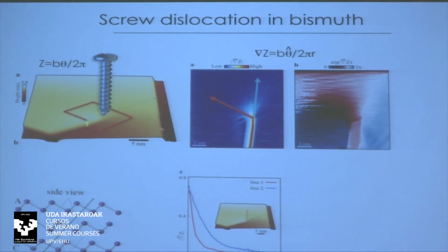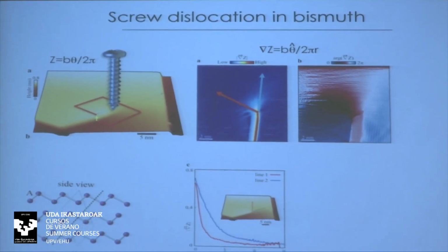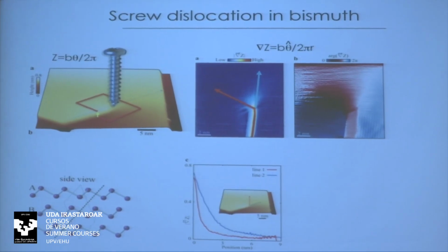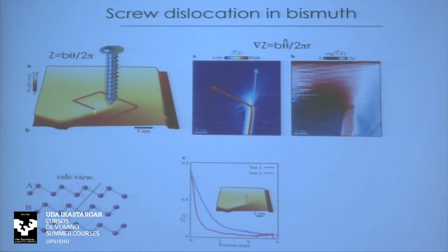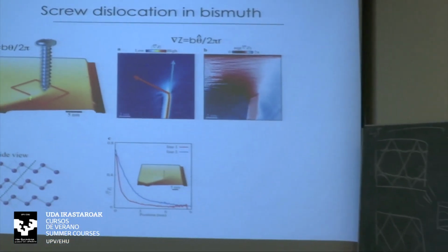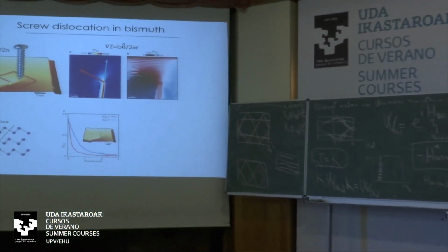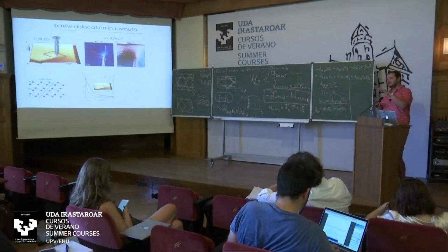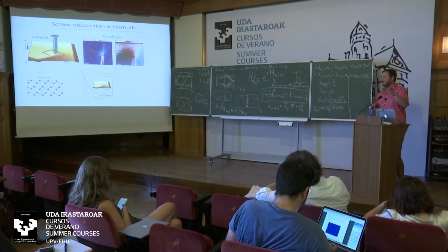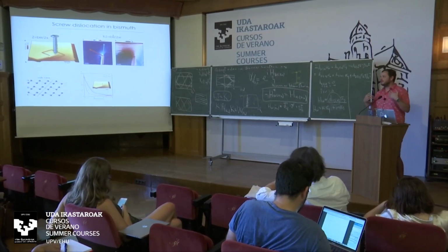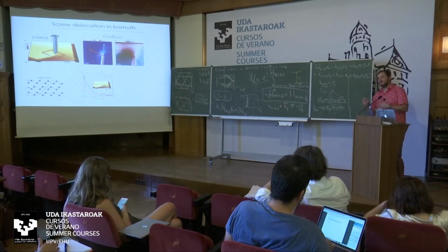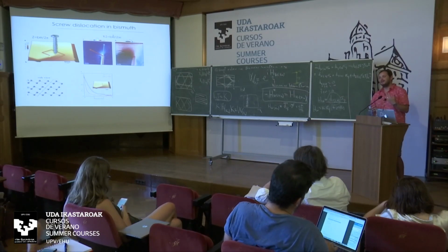So also it's not clear how exactly you can induce a screw dislocation, a single bilayer screw dislocation, along an ABC stacked crystal, which also puzzled us for some time, because by the time you finish a single rotation, you also have to induce a lateral shift in order to connect to the shifted bilayer below, which is very expensive energetically.